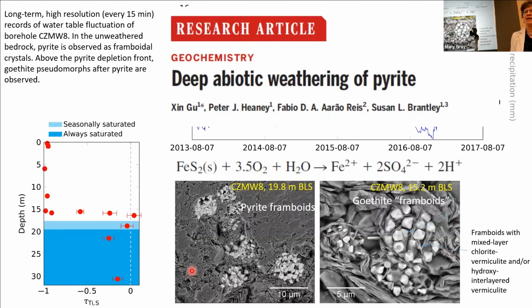And the argument we made was that bacteria could not get into the pores where the pyrite oxidation is occurring. So we were actually able to get samples from our core where you can see a fracture and there'll be pyrite oxidation at the edge of the fracture.